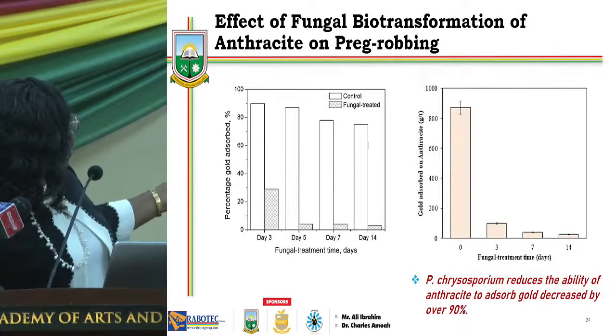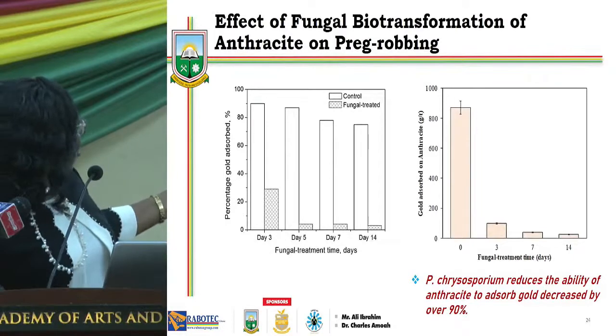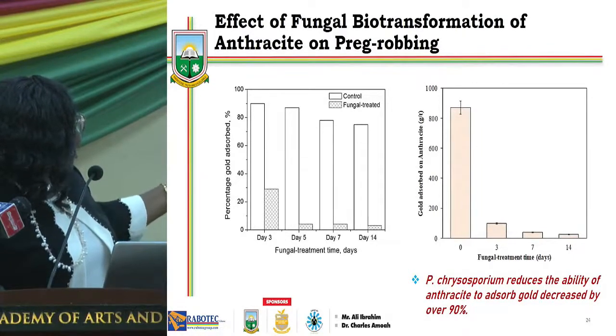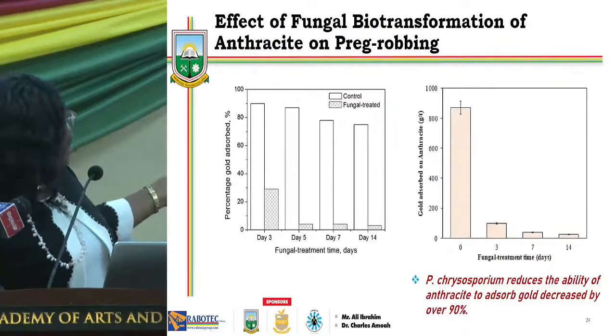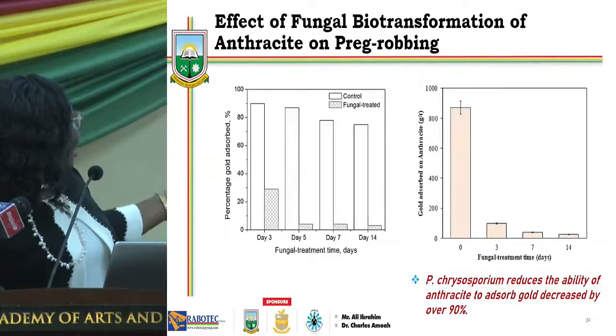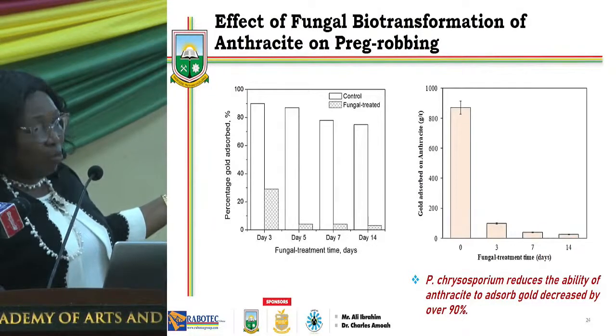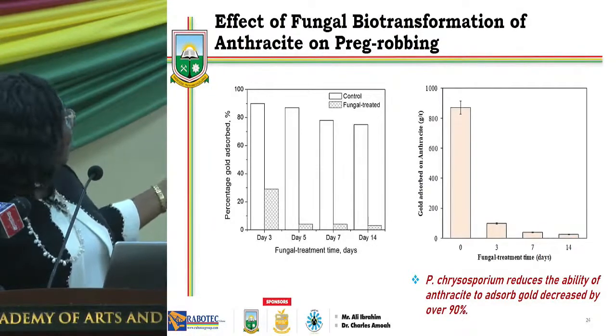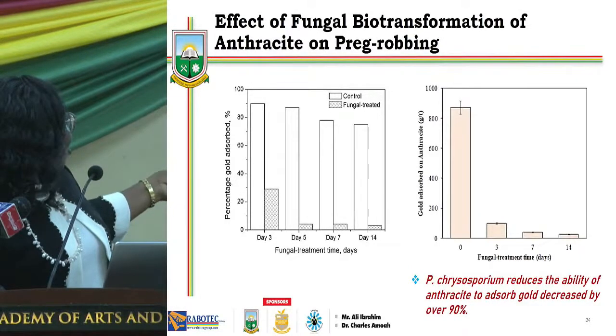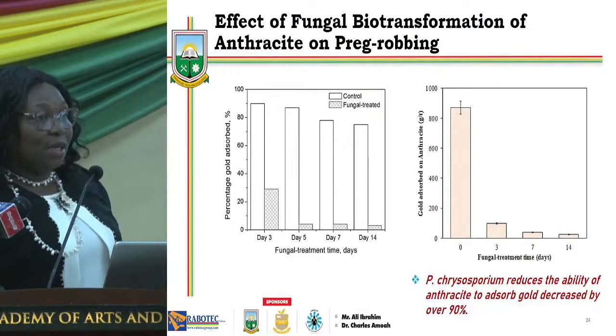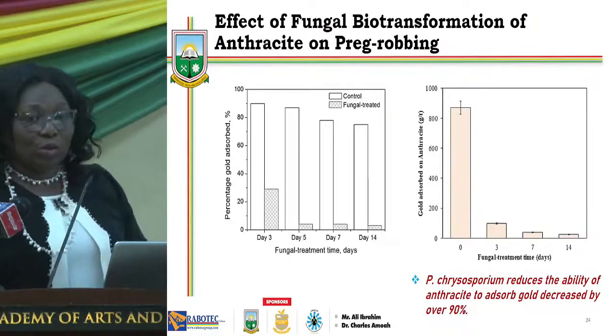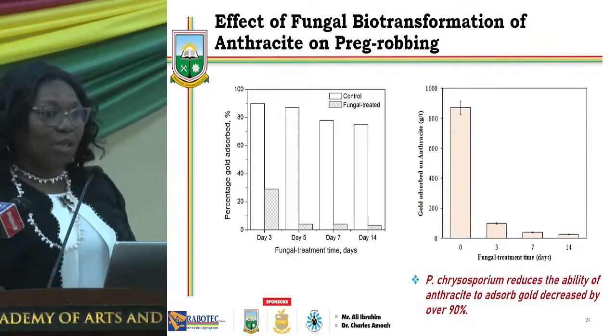This first figure is showing percentage gold adsorbed. The empty bars are the controls, and the shaded ones are the fungal treated carbon. So, as received control against fungal treated carbon. From the diagram, we can see that the major changes observed are as a result of treatment with the fungus.